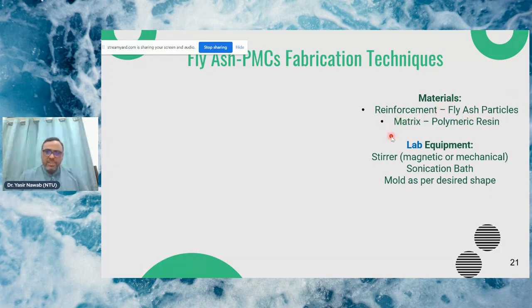The most challenging point in making these composites is the uniform mixing of fly ash particles into the matrix. So for that, we use stirrers like magnetic stirrers and high speed mechanical stirrers, and sometimes we use a sonication bath as well in order to ensure the dispersion is uniform.